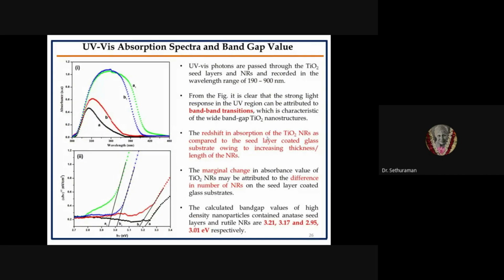And also we studied the absorption spectra and band gap value by using UV visible studies, and we found a redshift in absorption of TiO2 nanorods as compared to the seed layer. Here A, B is the seed layer and A1, B1 is the nanorods. We found the redshift in absorption of the TiO2 nanorods as compared to the seed layer coated glass substrate, owing to the increasing thickness and length of the nanorods. The marginal change in absorption value of TiO2 nanorods may be attributed to the difference in the number of nanorods on the seed layer coated glass substrate.